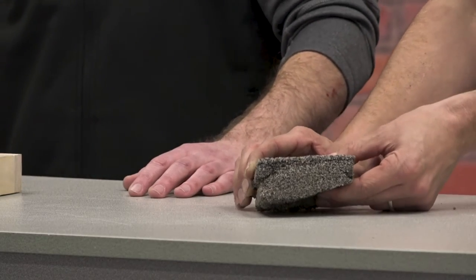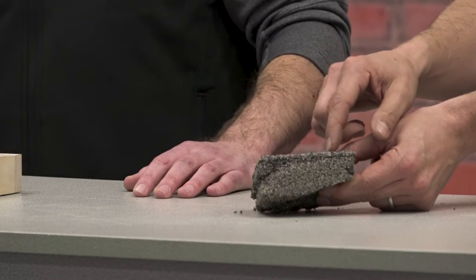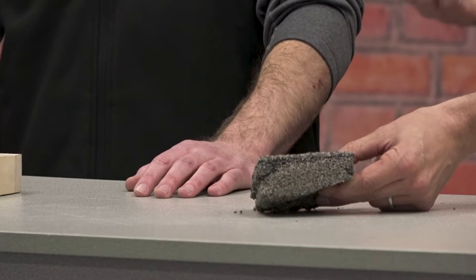Yep, I'd say an inch and a half or so, if you can get that, is certainly ideal. But anywhere from a half inch to an inch and a half is typical normal polymeric sand behavior, right? We want that polymeric sand to form a nice, thick, durable crust, glue itself to the sides of the paver. It's got some flexibility, right? Yep. It can move with interlocking concrete pavers. And that thick crust is supported by the densely packed material underneath, that material that we packed in well during our compaction step, right?